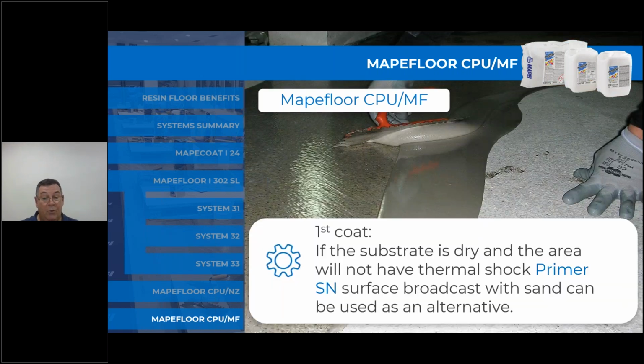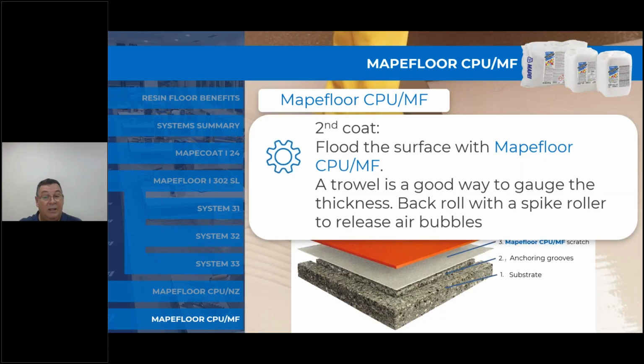You can use as a first coat, if the substrate is dry and the area isn't subject to thermal shock, Primer SN and surface broadcast with sand as an alternative to a scratch coat of the Mapefloor CPU MF. The second coat is a flood of the surface with the Mapefloor CPU MF, as is typical with a self-leveling floor. A trowel is a good way to gauge the thickness, and then back roll with a spike roller to release any air bubbles.